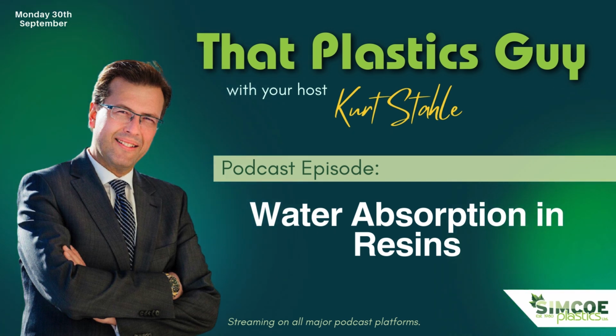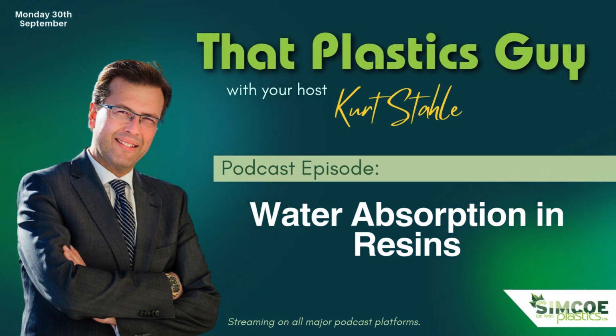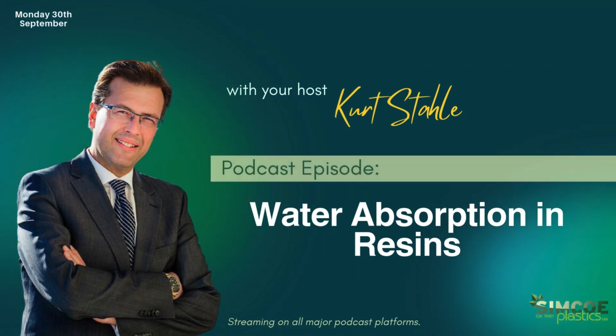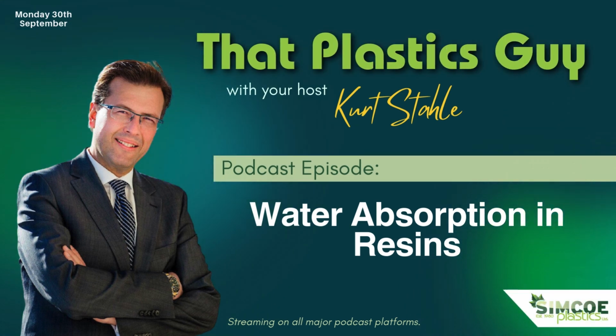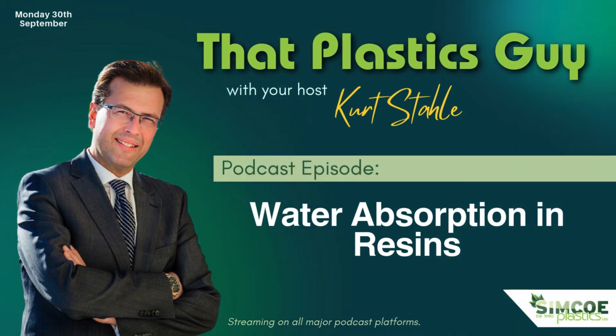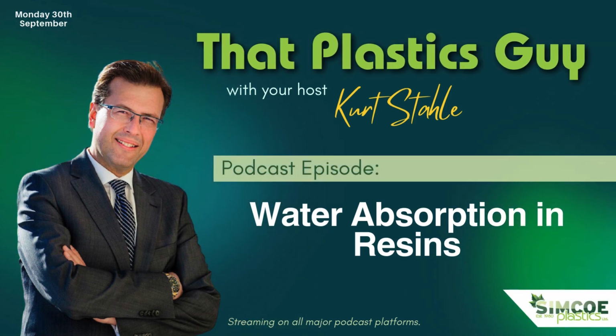So I do want to just touch again. The permeability may increase, but we also need the nylon to have absorbed regular ambient moisture in order for it to get to its conditioned state where physical properties are optimal. Not super heavy, laden with moisture, not dried. You have to have a regular level of moisture for nylon to have its maximum characteristics, and typically you'll see that on the data sheets as to how they condition it.